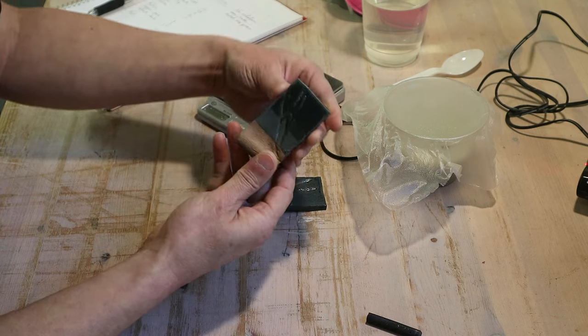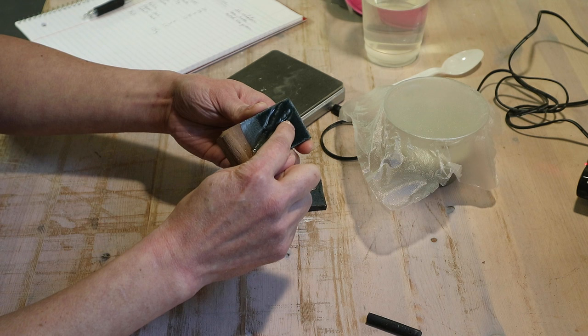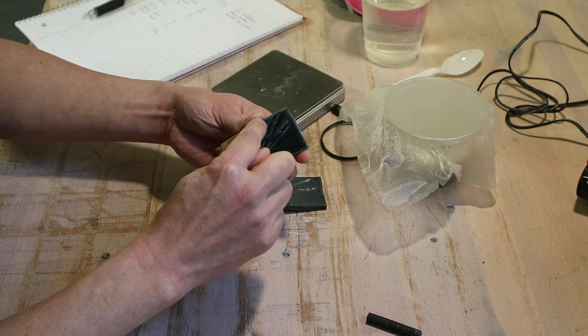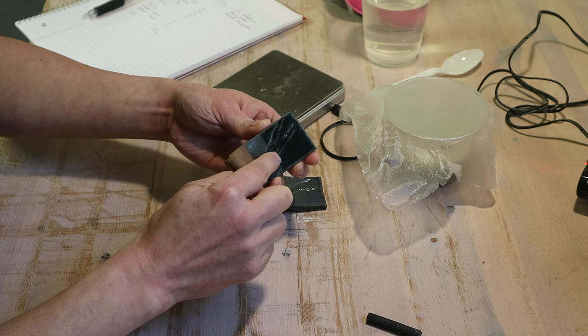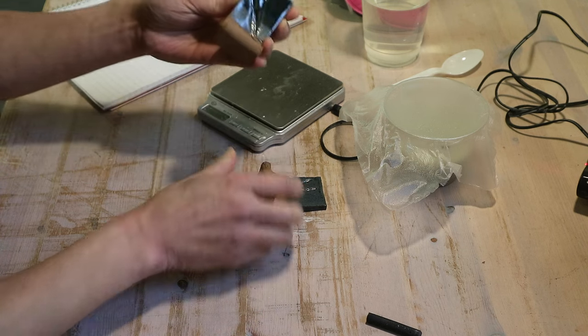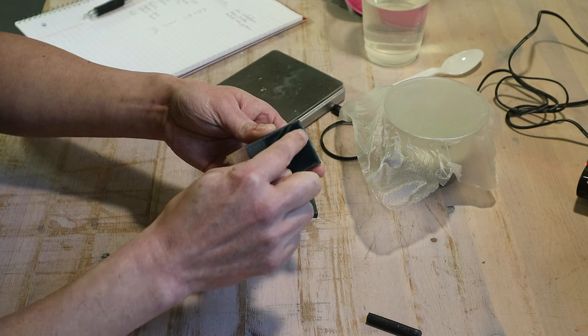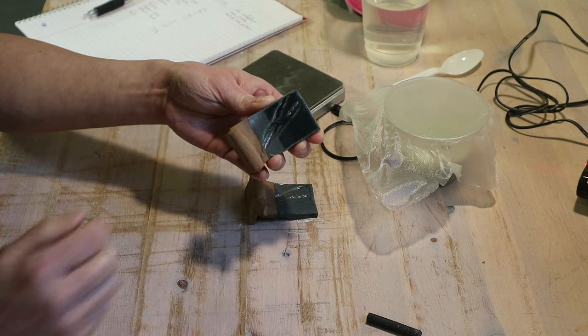Also, when we look at the side with the stamp, the thicker application causes the glaze to break around the edges of the stamp and also on the edges of the tile. The glaze gets lighter and more matte when it hits an edge. This didn't happen on the single dip application. I really like glazes that do this. When I see this happening, I start thinking of ways to take advantage of it.